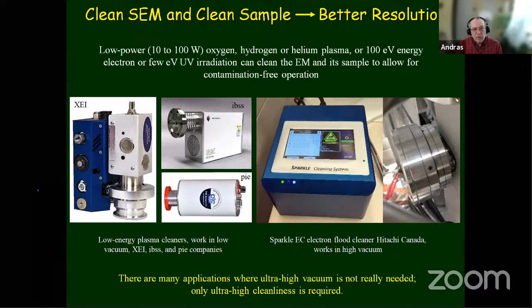The other advantage is that this works in high or ultra high vacuum, and that makes the removal even faster. So even with much lower energy, about 4 watts going into it, the cleaning rate is quite sufficient. So again, there are many applications where we don't really need ultra high vacuum, but ultra high cleanliness. So next slide, please.